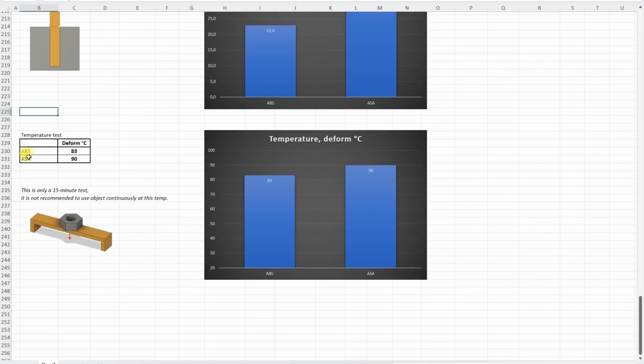On a temperature test, well, the ASA performed a little bit better compared to the ABS, but a little bit lower compared to the average similar materials. Now some quick conclusions for the end. Well, if I have to choose between these two materials, I would definitely say that ASA is worth the price difference. I also checked these materials, compared them to other similar materials from my summary table, and I could see a little bit weaker tensile and shear stress of these materials, but on the other side better layer adhesion. Also again a little bit weaker temperature resistance, but better printability. So even on these very high flow rates, I had zero problems so far printing these filaments.